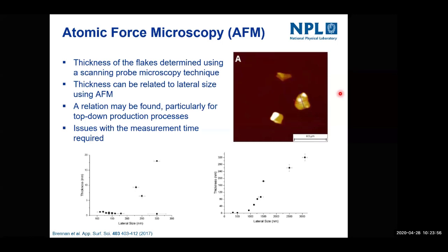Now, I'm not saying number of layers, because that's not really what you're measuring with AFM. You're measuring the thickness, which can be related to the number of layers. And by looking at individual flakes with Raman spectroscopy, you can get complementary information and validate that these flakes are the number of layers that you believe them to be. Also, you can imagine there are issues around this technique, such as contamination and comparing the thickness to number of layers. And in terms of speed, this tends to be a bit of a bottleneck when you're trying to measure these flakes. It's a slower technique than SEM, and definitely slower than Raman spectroscopy.